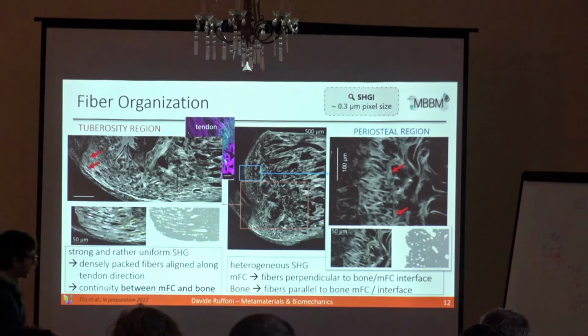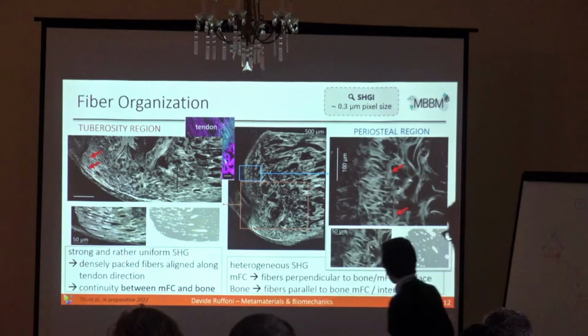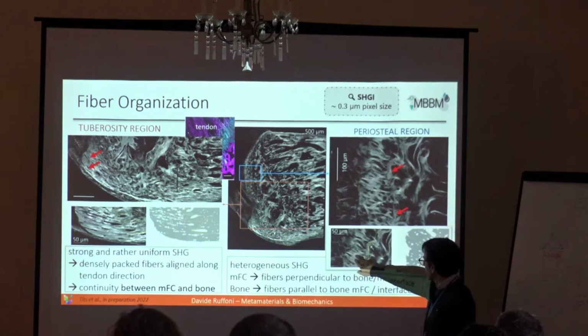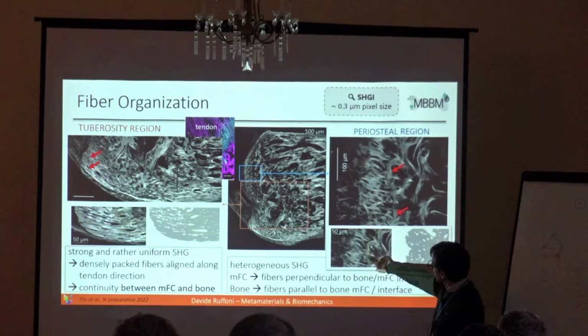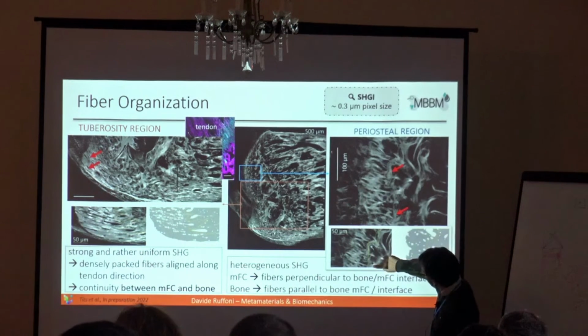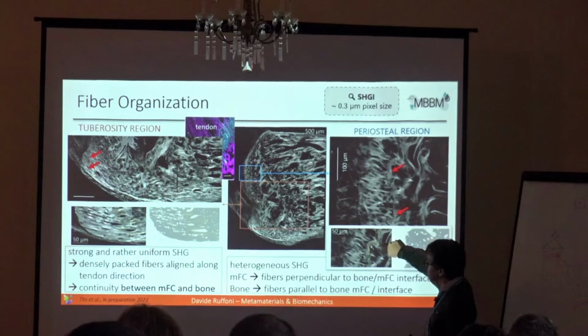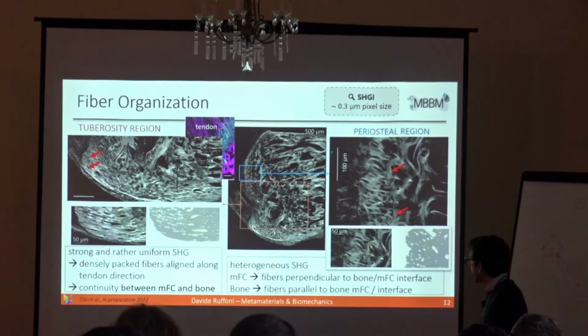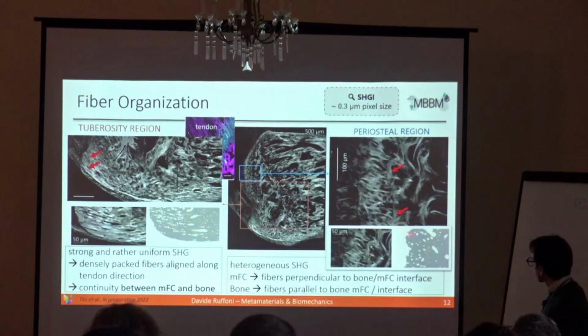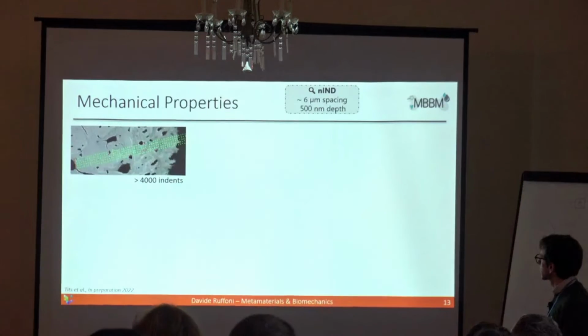Another thing that I like to highlight is that, from the fibrocartilage side, fibers tend to arrive more perpendicular at the interface with bone, and from the bone side, fibers run more parallel to this interface. So there is some kind of change in fiber orientation at the interface between fibrocartilage and bone, which is not present when a tendon is inserting. So this is how we are investigating those aspects.